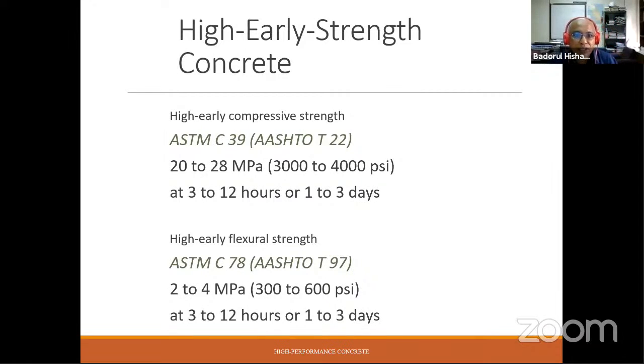So the high early strength, according to the ASTM, between 3 to 12 hours, you can achieve, or between 1 to 3 days, you can achieve 20 to 28 megapascal. At this strength, you can strip off your formwork. And high early strength, this is in compression.